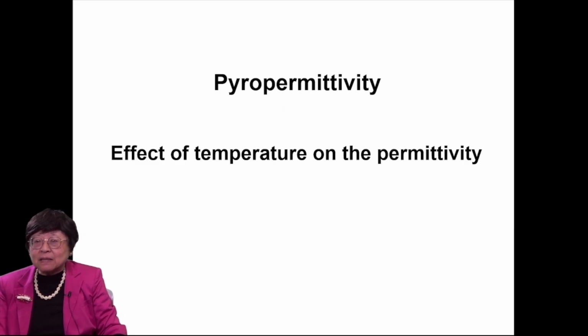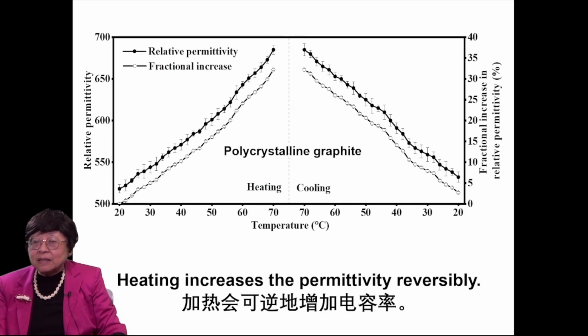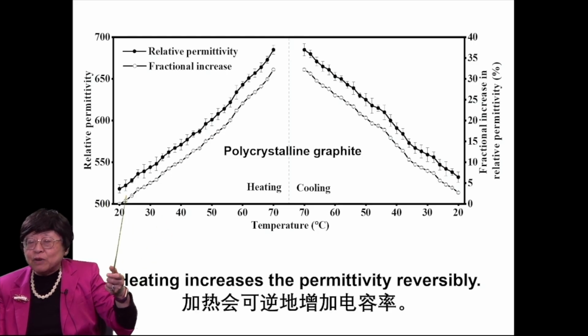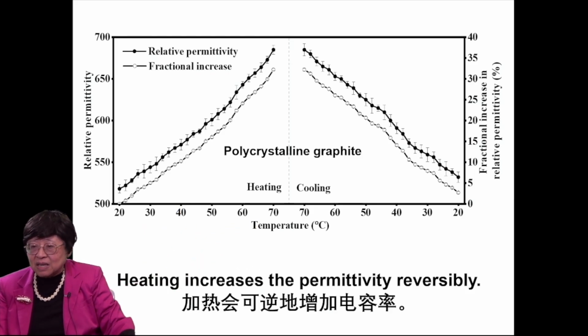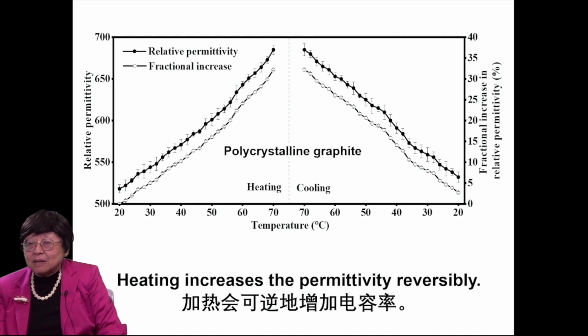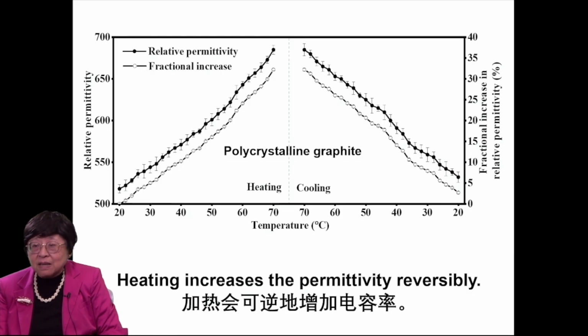Pyropermittivity means the effect of temperature on the permittivity. And shown here is polycrystalline graphite, and the relative permittivity increases quite reversibly upon heating. It's just heating to 70 degrees C. So one can use the permittivity to sense the temperature. And also it can be used for energy conversion, converting thermal energy to electrical energy.